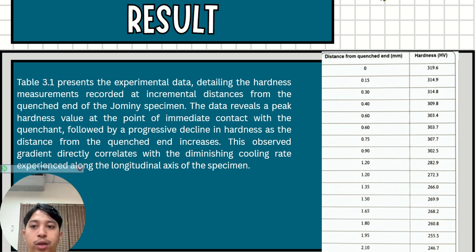As the distance from the quench end increases, there is a gradual decline in hardness. This trend corresponds to the decreasing cooling rate along the length of the specimen, resulting in the formation of softer microstructures such as bainite and pearlite. The hardness gradient observed across the specimen demonstrates the direct relationship between cooling rate and material hardness, highlighting how thermal treatment affects the mechanical properties of steel.